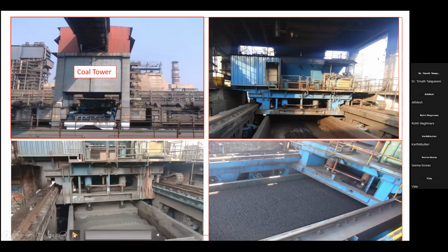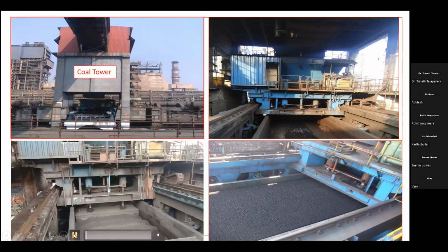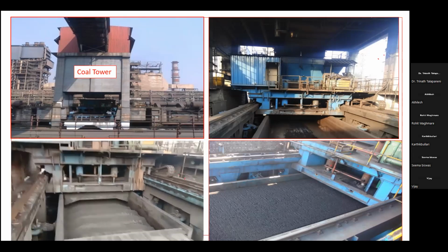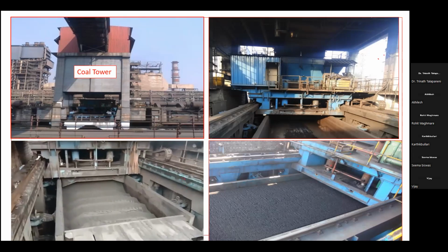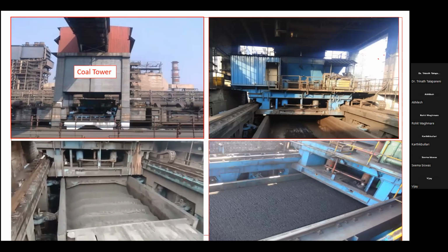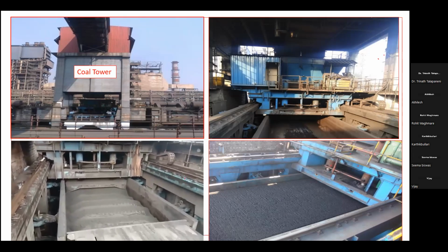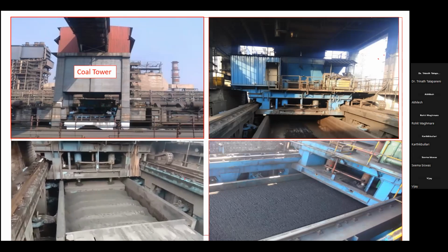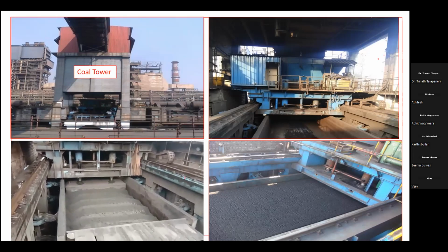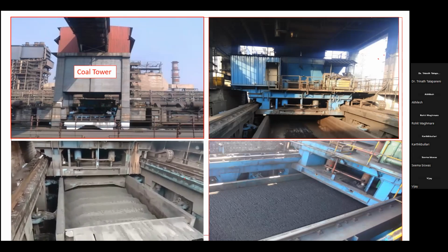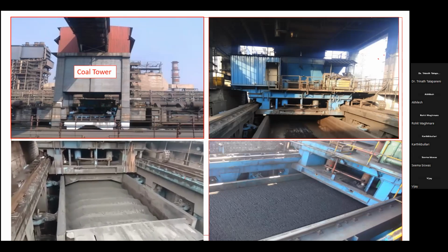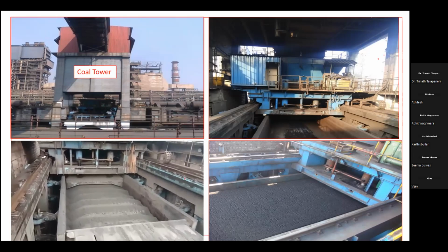There is a small video which shows how the stamping is taking place. This is a movable hydraulic stamping machine. Whenever the charge falls down from the bunker, a load is applied, and we can also keenly observe a certain amount of moisture. As I told you, 10% of moisture we add acts as a binder. During the stamping process, a certain amount of water is sprinkled in the vicinity of the stamping area.